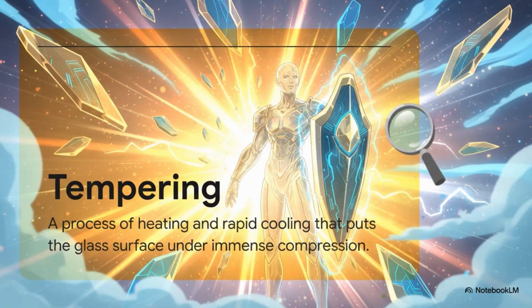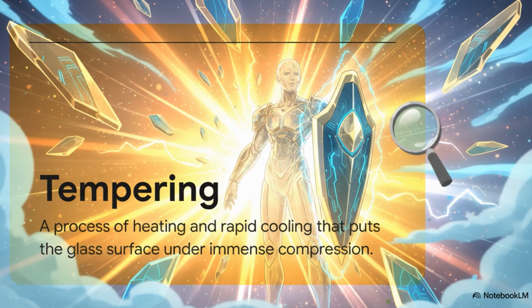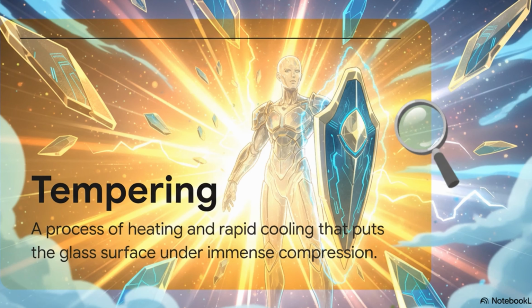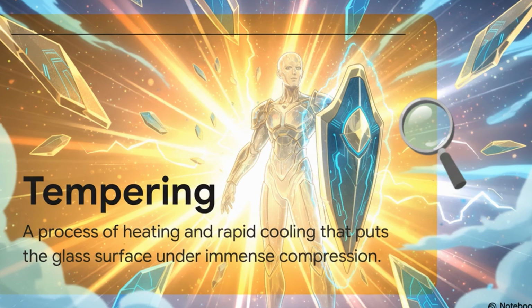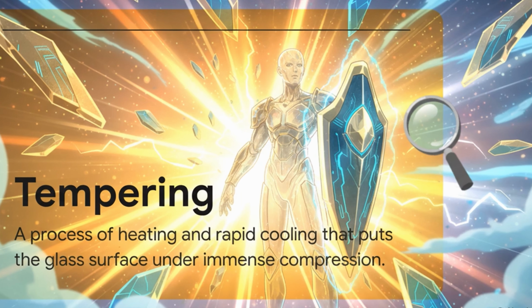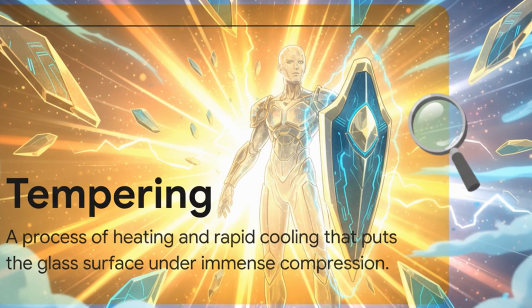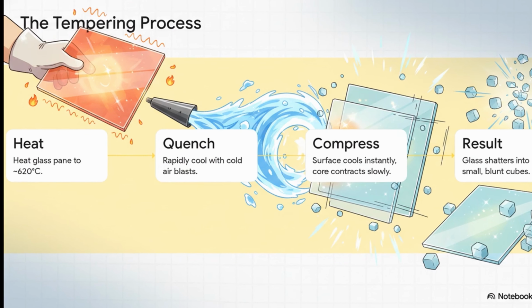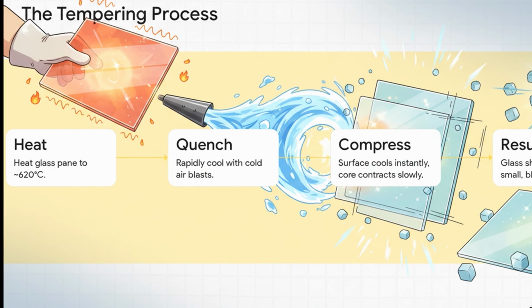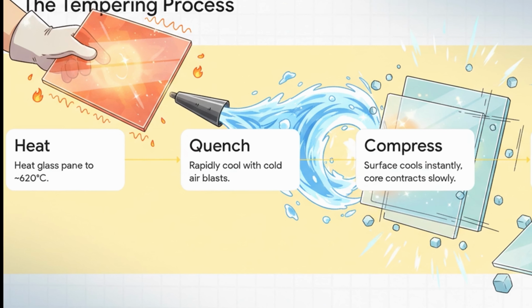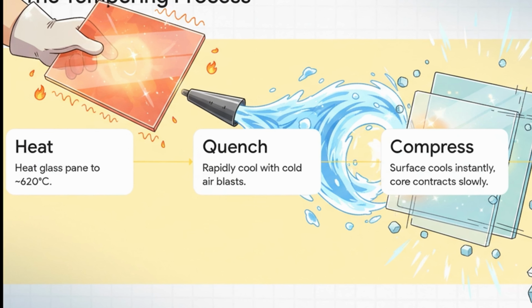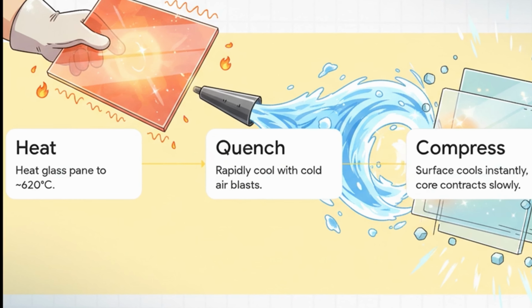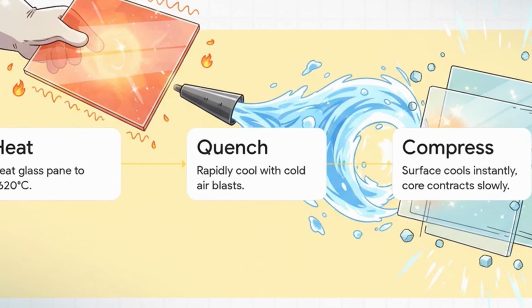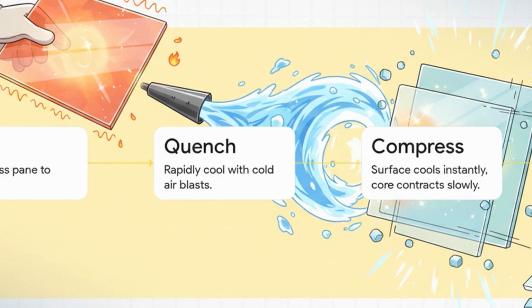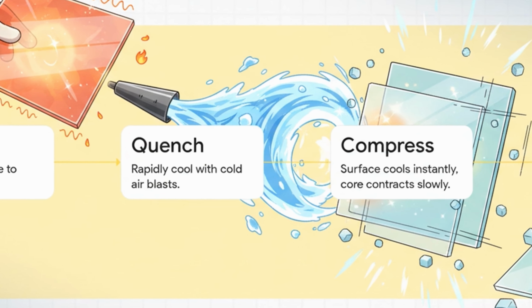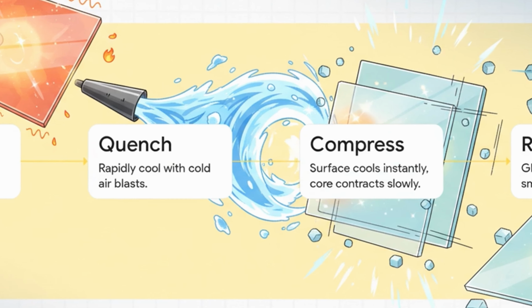So, what's the first solution? It's a process called tempering. And the best way to think about it is like giving the glass its own invisible suit of armor. Seriously, this armor is created by putting the outer surface of the glass under a ton of compression. And how do they forge this armor? It's all about heat and cold. First, they heat the glass up to about 620 degrees Celsius, so it's almost soft. Then, bam! They blast it with jets of cold air. The surface cools and hardens instantly, but the inside is still hot and cools down way slower. This creates this insane tug-of-war, putting the outside under massive compression.